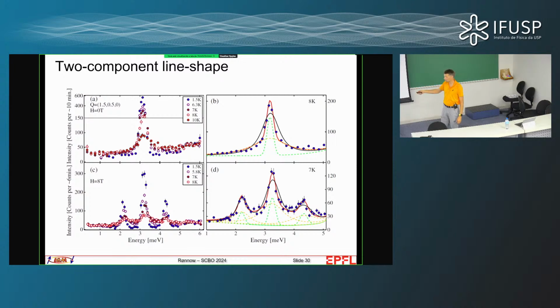Okay, we see a broadening, that's all fine, but when we look more carefully, we can't fit this with a single decay time. In fact, we get one decay time, one lifetime, which decays very fast as we increase temperature, and another one that stays much longer. So somehow it's like there are two separate types of response from the system. Theorists were no use.